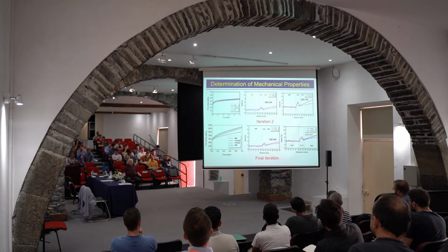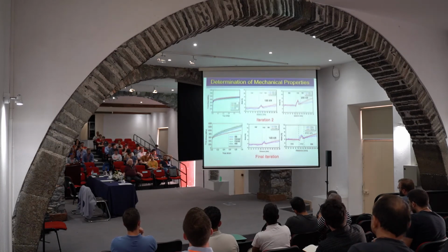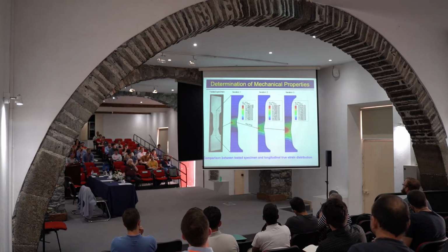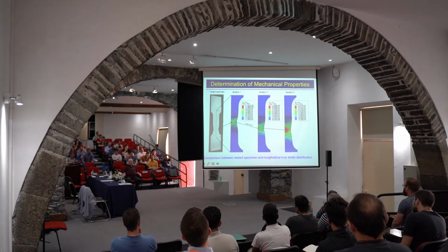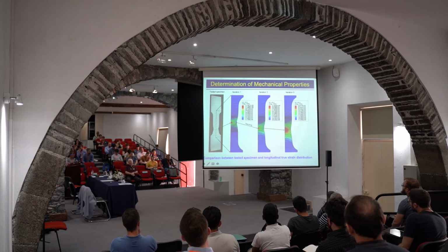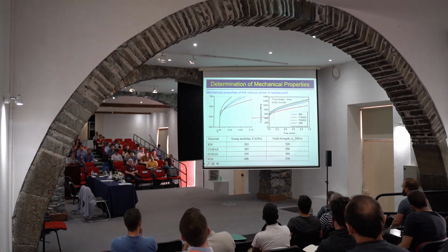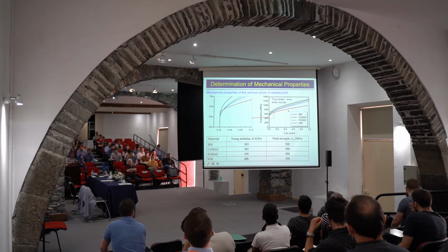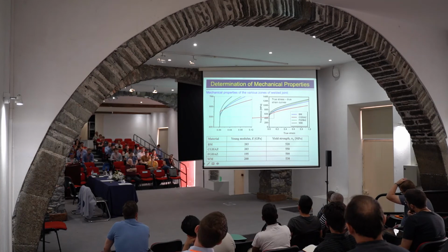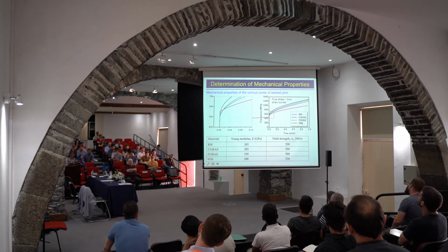So it is a combination of experimental and numerical effort to get something like this. We knew how it should look, how it looked in the experiment, and then by iteration procedure, by adjusting the properties, we are getting this very close behavior to the real one. So in this way we were able to get true stress, true strain curves, which we needed for this analysis, and you can see them for base metal, coarse and fine grain, heat affected zone, and weld metal.